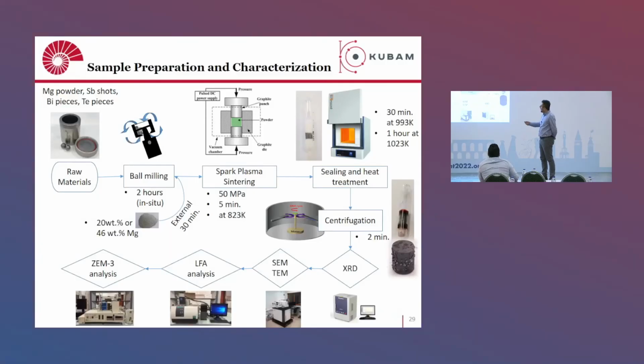Okay, so you can tune the properties by adding sodium or other elements, because magnesium is 2+ here in magnesium 3 antimony 2. If you add sodium, it means you are replacing 2+ with 1+. So you are pushing it to P-type material. Our motivation here is not to touch P-type, because we know that P-type ZT is much lower than N-type ZT. That's why we were focusing on magnesium, not adding any alkali metals.